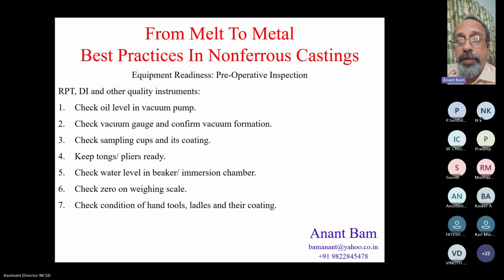Try to lift the lid at 80 millibar partial vacuum. No person by their own hands can lift the lid. The vacuum created is so strong that if you try to lift the lid, the whole machine, a 50 kg, 100 kg machine, gets lifted along with it. So that's a simple test of effectiveness of vacuum creation.